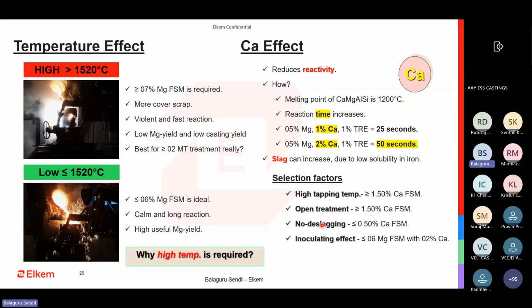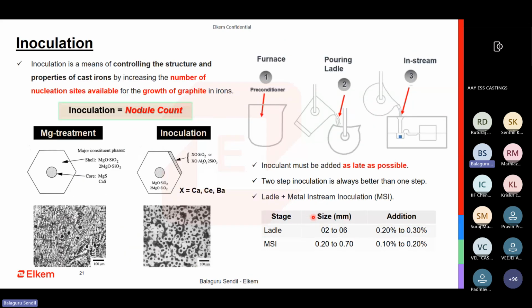I would prefer an FSM with 6% magnesium, 1% rare earth, and maybe 2% calcium, which makes sure that the FSM is calm. The reaction is very calm, not very violent, with very little fume generation, and whatever nodularization process is happening is at its best. And the inoculation is something that happens after nodularization.